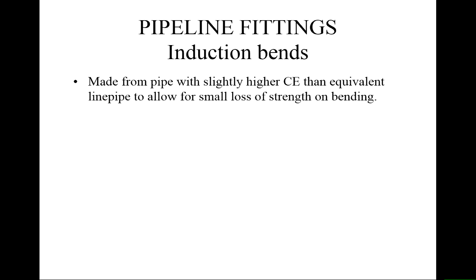So we've got to deal with the fact that you've heated this pipe and cooled it. That means that the grain size in the pipe will have changed, it will have grown, which means that the pipe has a slightly lower strength. And you have also to deal with the fact that when you stretch that pipe on the tension side, it plastically deforms, it has a slightly lower thickness. So to maintain the strength in that pipe, we need a pipe with a higher carbon equivalent. So what that's telling you is that we're not having as weldable pipe after it's been bent.